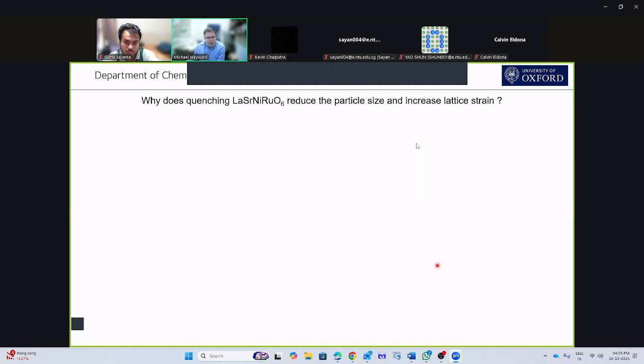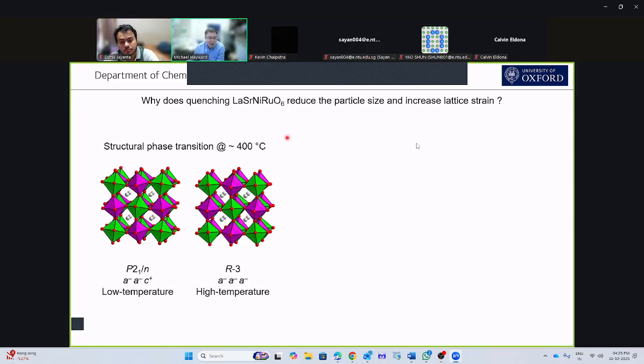So why does quenching lead to a change in the particle size and strain? Why does quenching make the particle size smaller and increase lattice strain? Well, it turns out there's a structural transition in this system. Like many perovskites, we get tilting and twisting transitions in the framework to accommodate the A cations within the framework of corner-linked B cations.